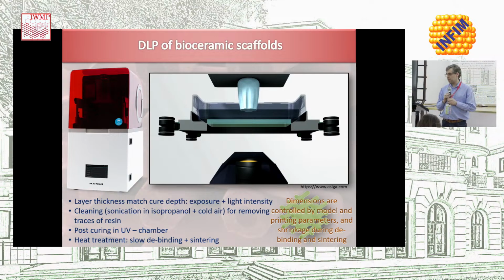The layer thickness. After printing, you take the sample out of the vat, and if you have pores, especially, which is the case in a scaffold, you may have some resin trapped in the pores. So you need to do a thorough cleaning process, typically using sonication in isopropanol, or maybe blowing air through the pores, trying to remove any traces of this residual resin.